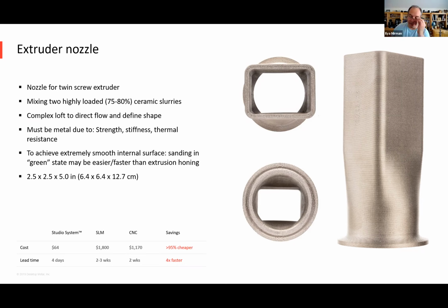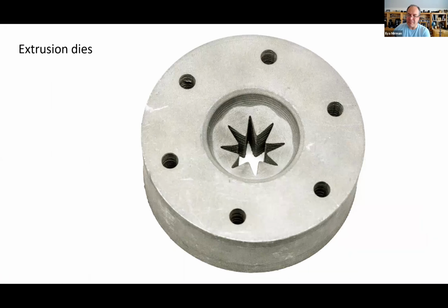It's an easy part to model. This is a loft. If you have a parametric feature-based solid modeler, you start from the circle, you draw the profile, you wind up with a rectangle. But it is not an easy part to actually reduce to practice, to create. You need a 5-axis machine, and our customer looked at a number of bids, and it would be $2,000-$3,000 to make this shape. You could see this is probably 6 inches or so, maybe 7. With the studio system, it's an order of magnitude less. It's $60 or $80, and you have the part. You can make complex extrusion dies that are either complex shapes or they're difficult or impossible to create.